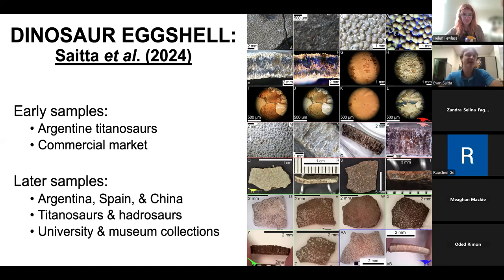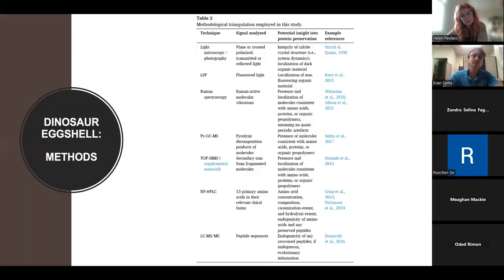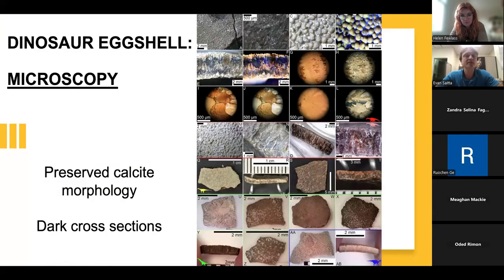And based off of the initial success, we then added to the samples later on, Argentina, Spain, China, not just titanosaurs, but also these duck-billed dinosaurs called hadrosaurs, using fossil samples from museum and university collections with better record keeping about their collection. Again, I try to use methodological triangulation whenever I can. And so just like in the previous study, using a variety of microscopy, spectroscopy, spectrometry on these samples. And when we look at these under light microscopy, you can see that although there is some recrystallization in some of these samples, overall, the morphology, the shape of the calcite structures within the eggshell, such as the surface ornamentation on the eggshell, which are very diagnostic, as well as these columnar calcite crystals in cross section, are still preserved. Many of these eggshells have very dark cross sections, consistent with, say, high organic content.